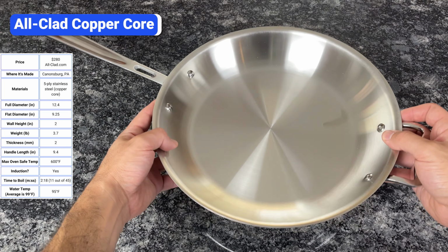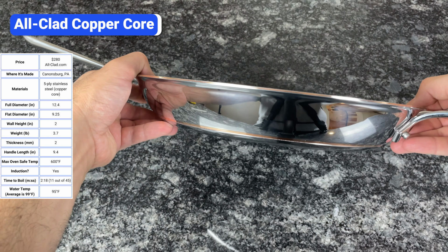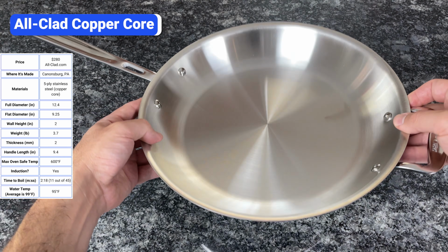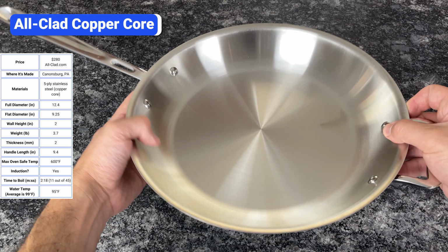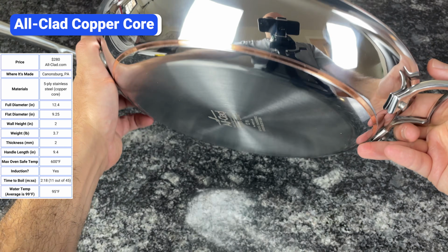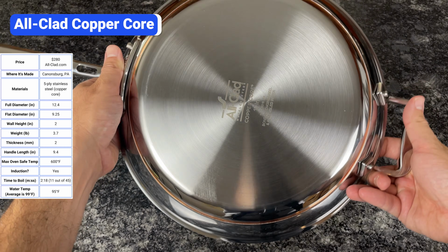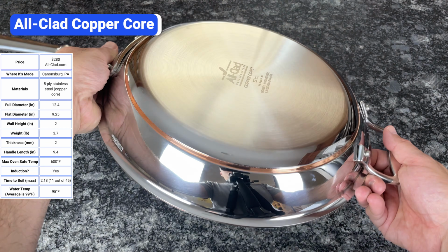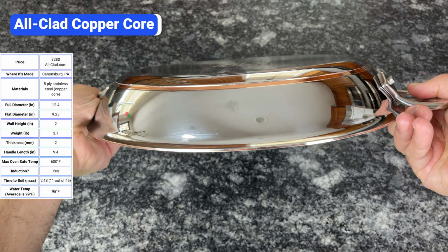All-Clad copper core is similar to All-Clad D5, but the handle is longer at almost 9.5 inches, the exterior is polished, and instead of a thin steel core, it has a thick copper core. The copper results in fast, even heating, but it makes this pan heavy and much more pricey.